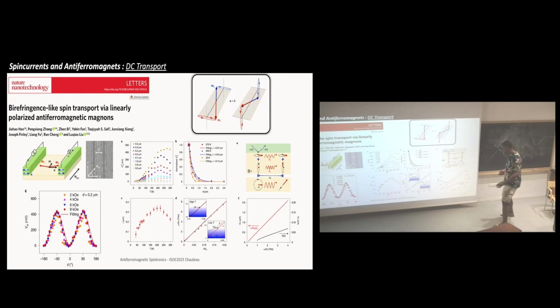And what is nice in the paper is that they really put the finger on the way you can convey this spin information. The thing you need to know is that in Fe2O3, those two branches are close together. But in NiO, which I was talking about just before, those two branches are far apart, because one is at 240 gigahertz and the other at 1 terahertz. So intrinsically, they will not convey the spin information over long distances. This is what I like about this study.